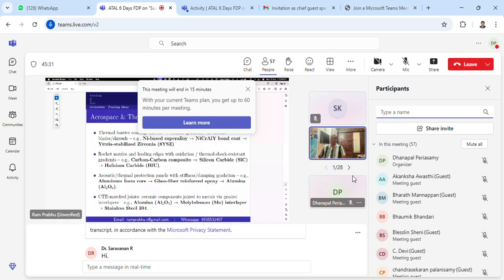So in order to improve that, it is coated with silicon carbide. On top of it, if your re-entry velocity is very high, they will coat hafnium carbide on top. That is a much higher, ultra high temperature resistant ceramic material. So in your proposals, what you can write for these applications is that you can apply this material gradient and characterize its properties to look at whether the material fits the specific application we mentioned.